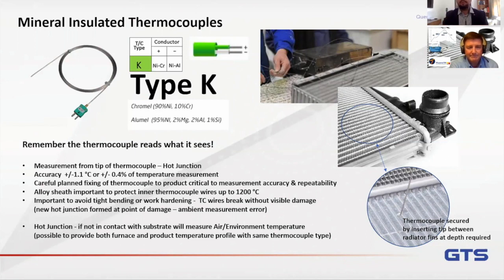Here at GTS, we recommend, when economy and finances allow, to use the thermocouples just once, preferably. That is very critical, especially if you go really high in temperature, close to 1,000 Celsius or 2,000 Fahrenheit. That's going to cause a lot of damage to the thermocouple. But that's, again, an economic issue we're not going to discuss right now. We need to emphasize that you need to treat your thermocouples properly.